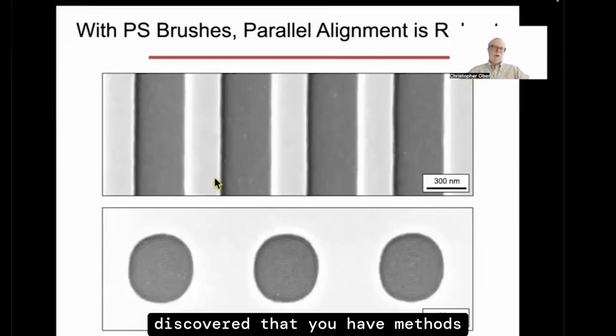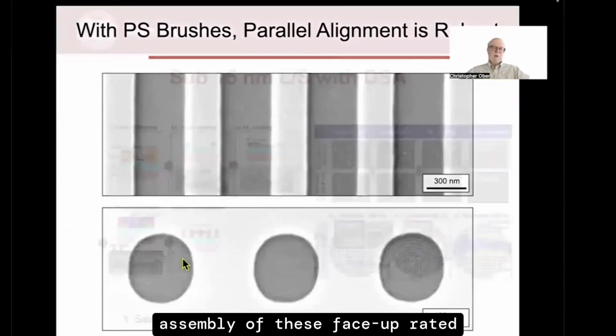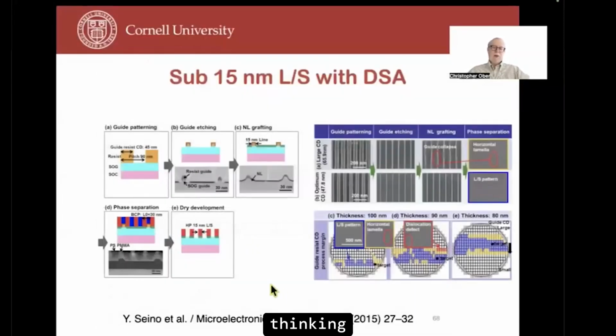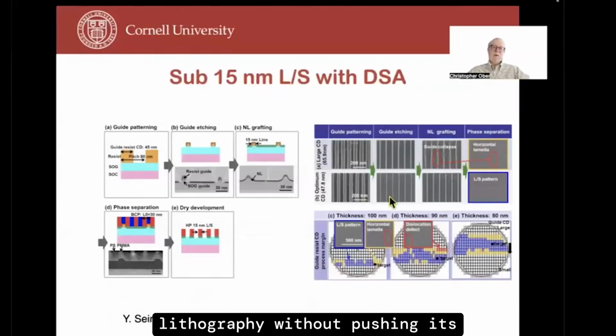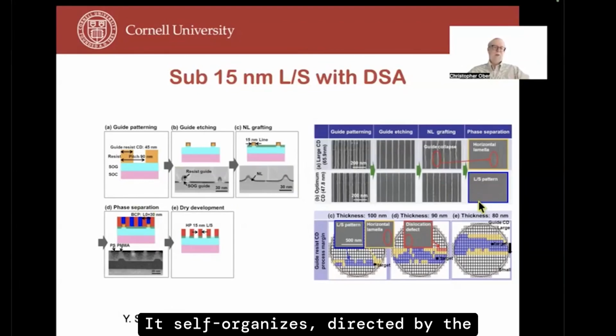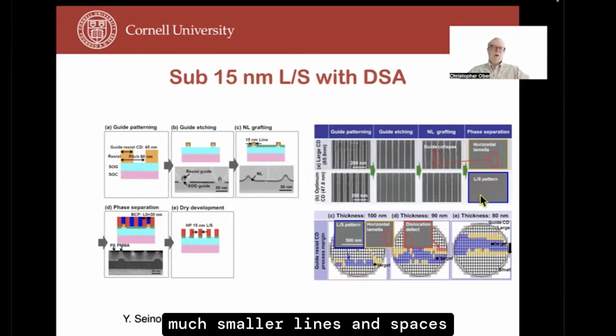So these were all things that were a dream in the early 2000s. But what eventually was discovered is that you have methods that you can use to guide the assembly. So I think you can see here the lines lying parallel in a trench, and you can also see the lines forming a bullseye. We're directing the assembly of these phase-separated structures. And so today, what people are thinking is that you can use conventional lithography without pushing its limits to create guideposts. You can lay down the block copolymer on the guideposts. It self-organizes directed by the guideposts, and then you can make much smaller lines and spaces without the need for these very costly, very expensive EUV systems.